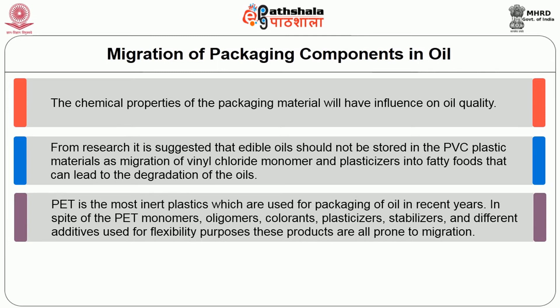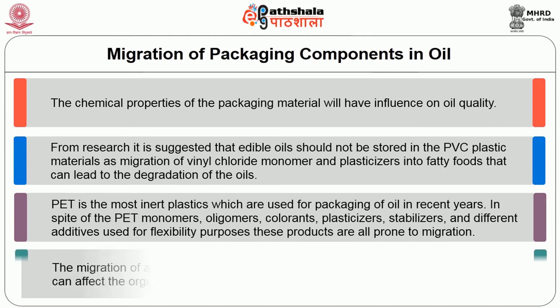PET is the most inert plastic used for packaging of oil in recent years. In spite of this, PET monomers, oligomers, colorants, plasticizers, stabilizers and different additives used for flexibility purposes are all prone to migration. The migration of acetaldehyde from the PET bottle is a major concern as its presence can affect the organoleptic properties of the oil.